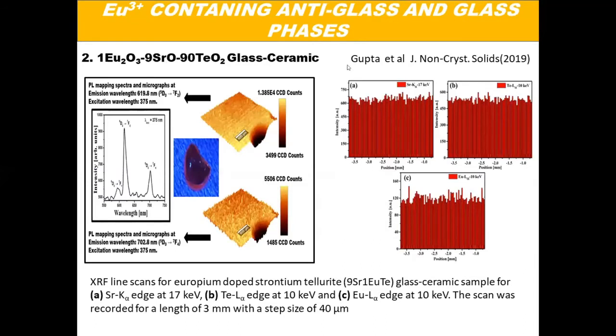This is another sample of europium oxide. A very small amount of europium oxide is introduced in strontium tellurite glass ceramic, and you see a very strong light emission at around 620 nanometer, 619.8 nanometer, and the excitation wavelength is 375 nanometer, near UV light, and you see red light emission. The sample was actually yellowish in color, but it is emitting red light because of fluorescence from the europium ions.